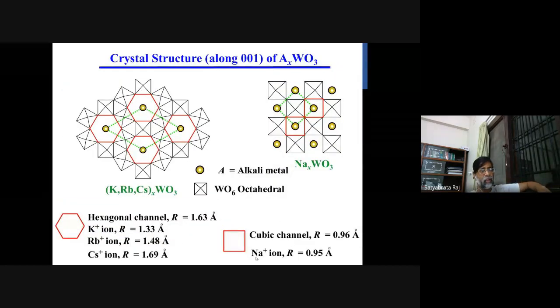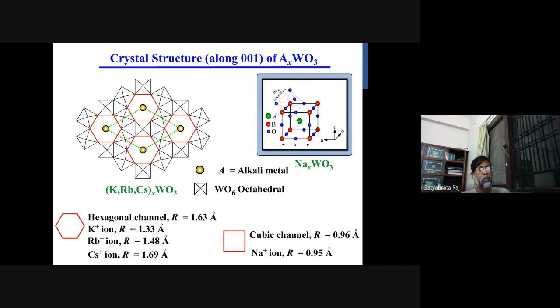So let's say for sodium, the ionic radius is 0.95 Angstrom, whereas in the cubic structure, the cubic channel is 0.96 Angstrom. So sodium can fit well with this channel. This is just like a cubic crystal with the sodium, the alkali metal, at the center, and you have an octahedral at one corner. I mean the oxygens are around the WO6 octahedral at the corners, and the W atom is in the center of this octahedral.